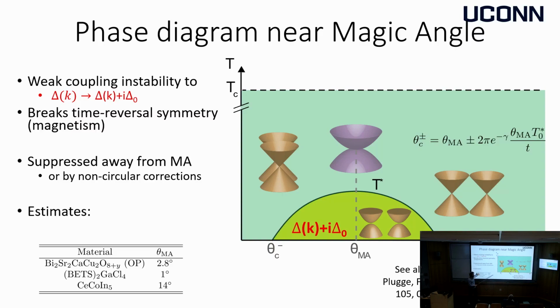Here, it's the physics of quasiparticles that get flattened out, and if there's some residual interaction between them, they can develop the secondary superconducting order. The prediction is that this should be close to the magic angle. As you twist away from it, you're going to lose this secondary phase. And we made some estimates for different materials.